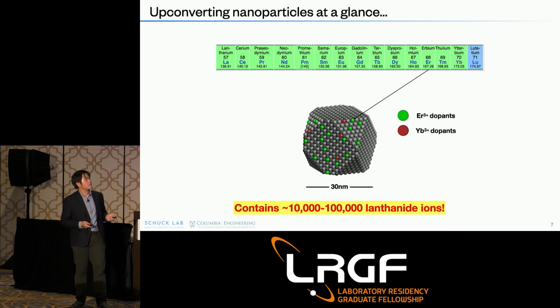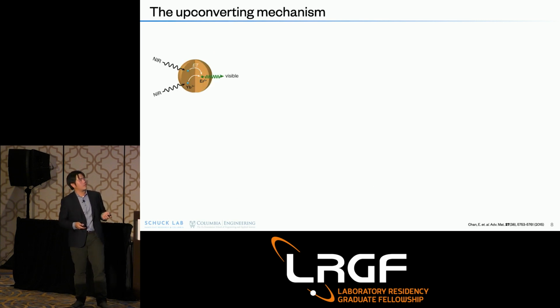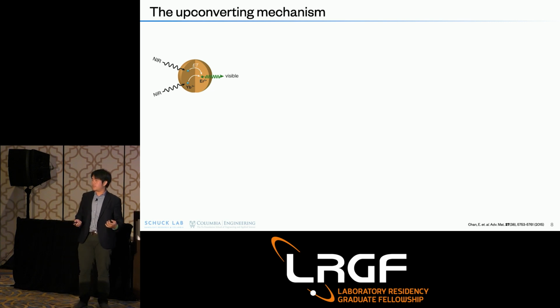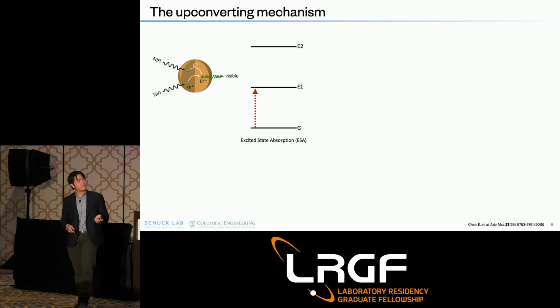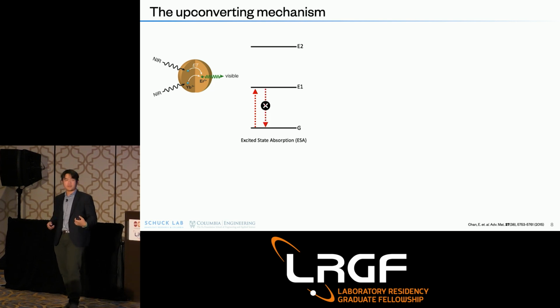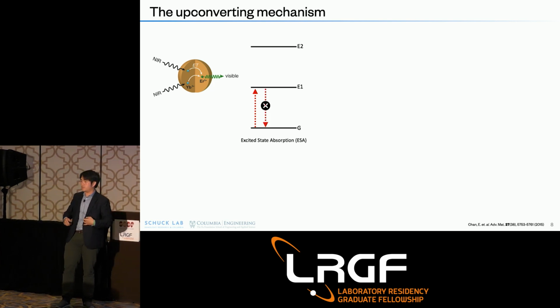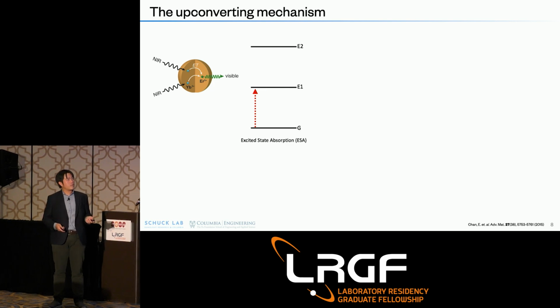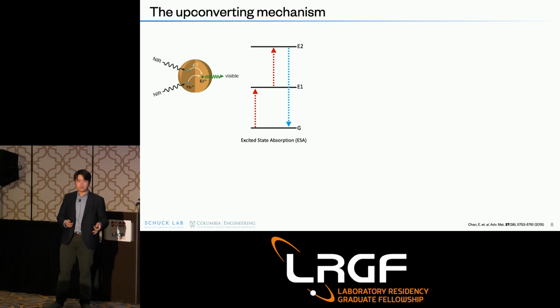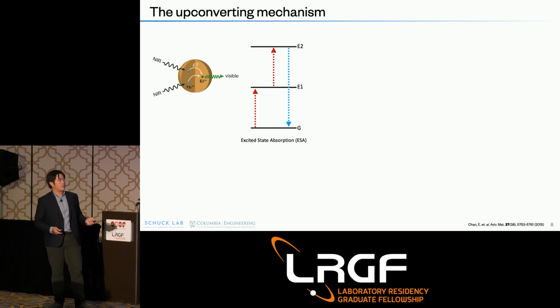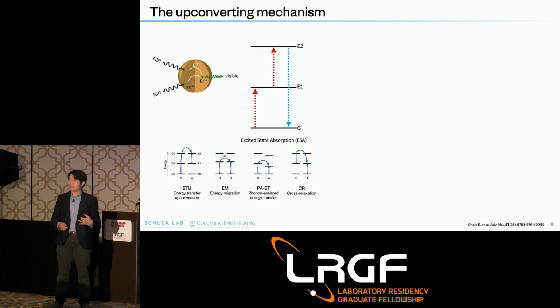And if you start to look at the upconverting mechanism, what you have is a nanoparticle. It absorbs an infrared photon, but because of the long-lived states in the first excited state, it does not relax immediately down to the ground state. Instead, it can absorb another photon from the first excited state to the second excited state, and eventually emit a visible photon of higher energy. Now, as I mentioned, there are about 10,000 to about 100,000 of these lanthanides in a nanoparticle, so you can really start to get very complex interactions.